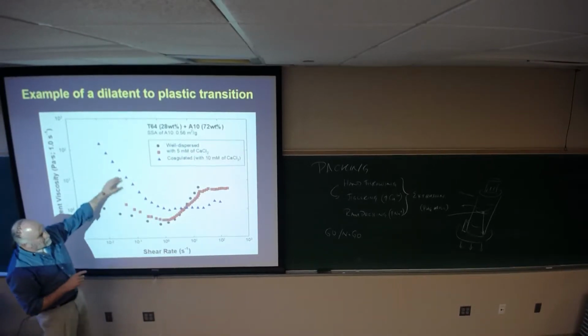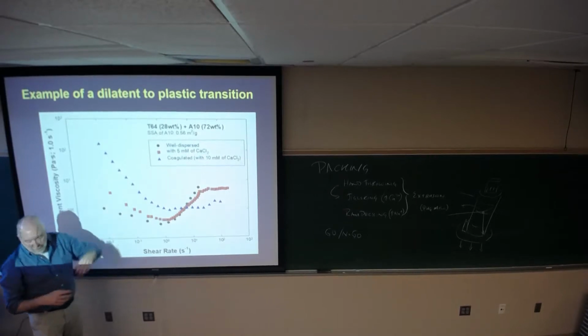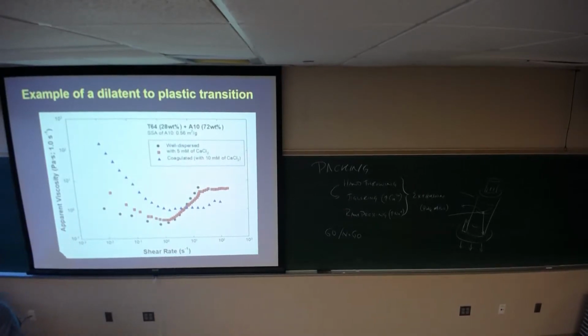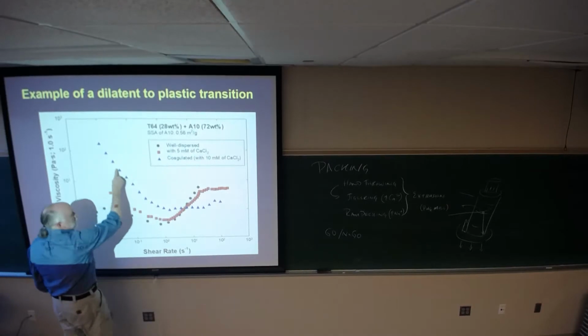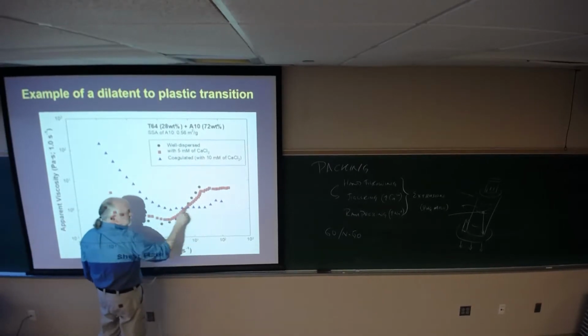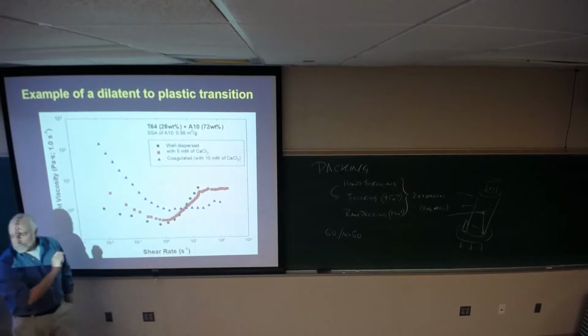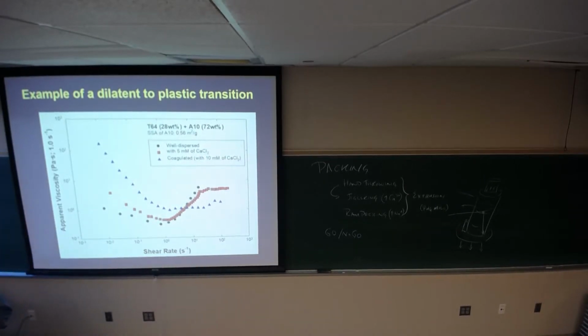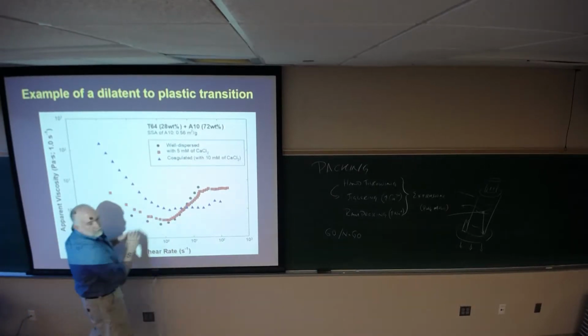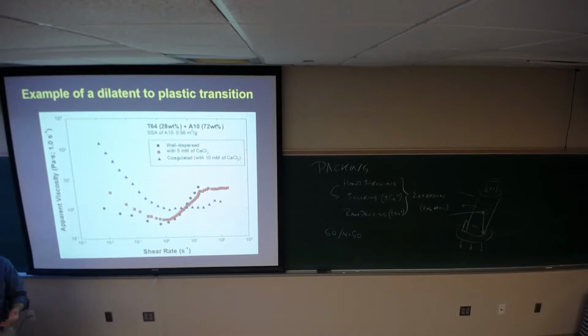What we found was that if we coagulate that with calcium, and then the calcium level is based on the amount of salt in the water, excuse me, not the amount of water in the pores, nothing to do with concentration. Then it comes down, and then what you see is you get this shear rate independent region, right? And that is plasticity. In other words, I'm shearing the system and I'm deforming without a change in viscosity over a shear rate range. This is my forming window, if you will. Okay, that I get, and then if I get past that, viscosity starts to go up.